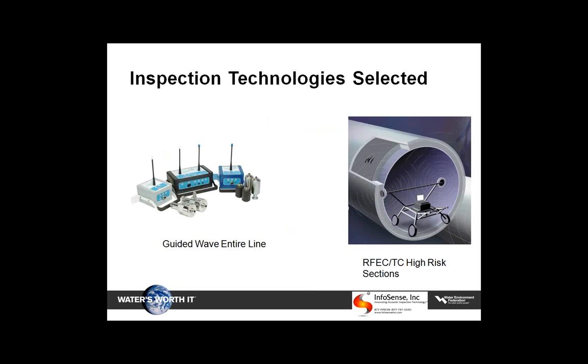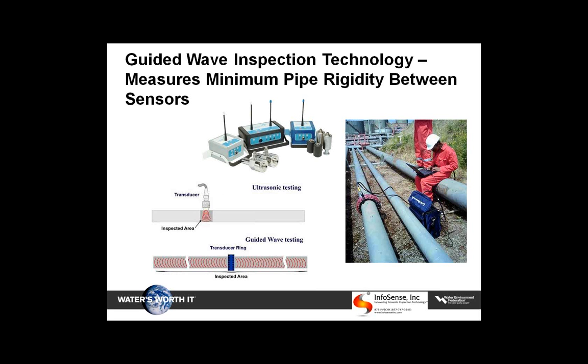We selected the guided wave to do the entire line because that was a very inexpensive technology, sort of at the $5 a foot range. And then we used that to focus the remote field eddy current on the high-risk sections. For the guided wave, basically, you need access to the pipe at 2 or more locations, and it will tell you information about the pipe between those locations. You can't get any more specific as to where the problem is, but it will tell you the weakest part of the pipe between those 2 sensors.